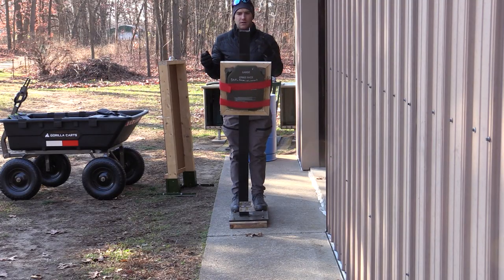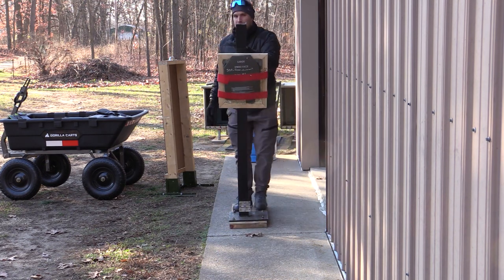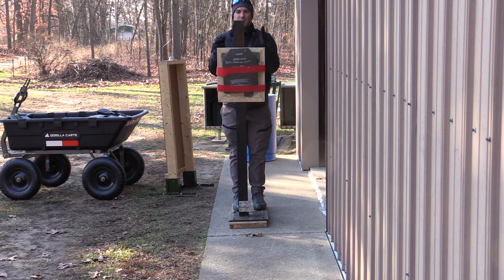While I'm not an NIJ lab, I try to stick to some of the NIJ protocols for consistency. I always test hard armor at 45 feet. I use a giant clay briefcase filled with non-hardening clay to act as a compressible media. Although it's only about 35 degrees outside today, that clay will be hard and will give us an under-representation of back face — it's just good to have it there. While these plates are not NIJ rated, the ceramic strike face has foam protectant. So we've dropped each plate on its face two times as a preconditioning test.